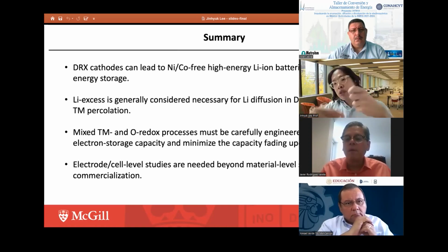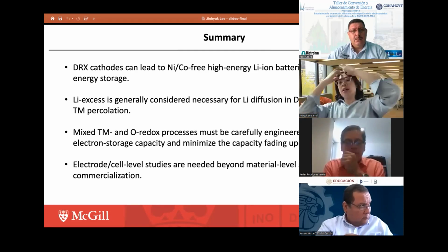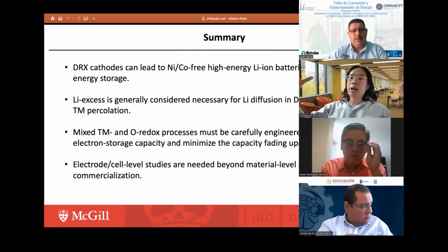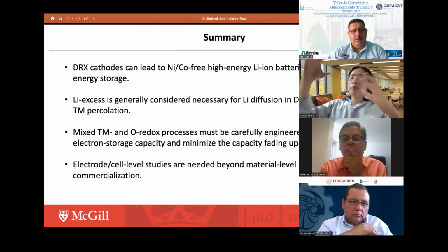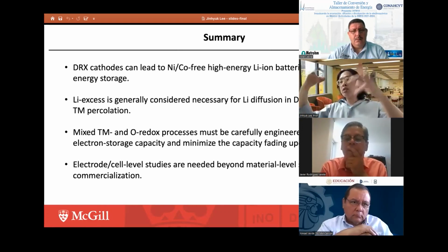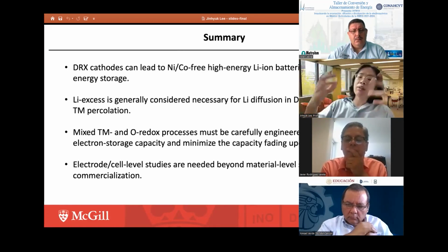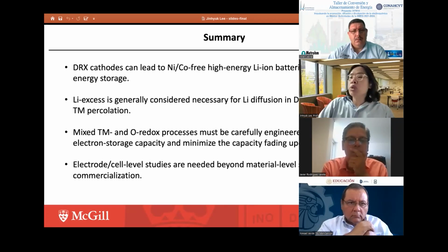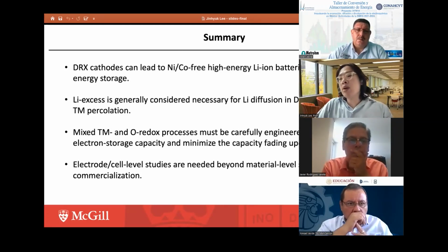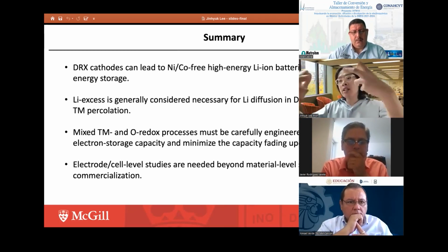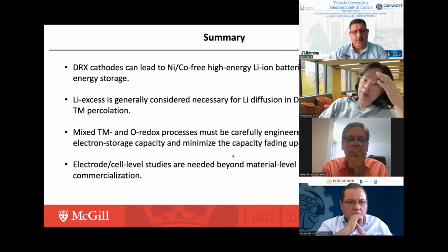So they have a smaller energy penalty when they try to make a disordered structure with the help of high configurational entropy. But in the sodium-ion case, sodium ions are much larger ions. So instead of mixing with each other, which generates lattice distortion, they would rather form some kind of layered structure. But it depends on what kind of transition metal you use, because for some transition metals the ionic radius may still be large enough to accommodate disorder with sodium as well.